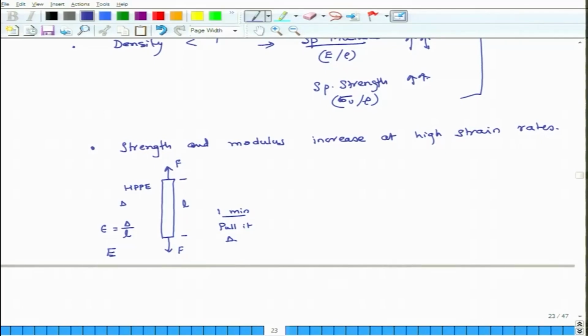So, what is the strain rate? Delta over L is the total strain, and I have pulled it over 60 seconds, that is strain rate. So, this is case 1. So, in this case strain rate is this epsilon naught divided by 60. Case 2. So, when I pull it in 60 seconds, in that situation the modulus is E, and also the strength is, let us say, sigma u when I am pulling it over 60 seconds. So, I am pulling it very slowly.